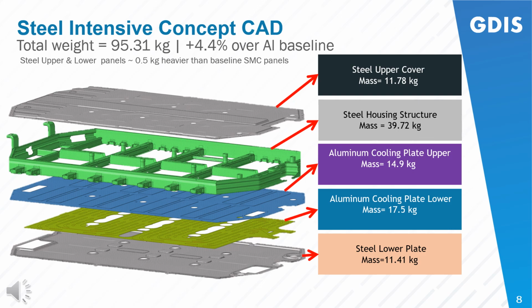Finally, if you look at the total weight of the assembly, the steel assembly weighs about 95.3 kilograms, as opposed to the 91.3 kilograms, which means the steel assembly is approximately 4 kilograms heavier than the aluminum baseline, which is about 4.4% over the aluminum baseline, and as we will see later, with equal or better performance.